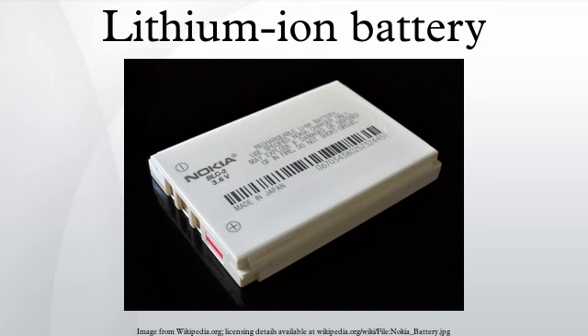In 2004, Chiang again increased performance by utilizing iron phosphate particles of less than 100 nanometers in diameter. This decreased particle density almost 100-fold, increased the positive electrode's surface area and improved capacity and performance. Commercialization led to a rapid growth in the market for higher capacity LIBs, as well as a patent infringement battle between Chiang and Goodenough. As of 2011, lithium-ion batteries accounted for 66% of all portable secondary battery sales in Japan.